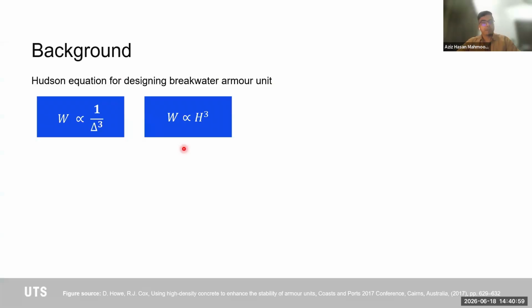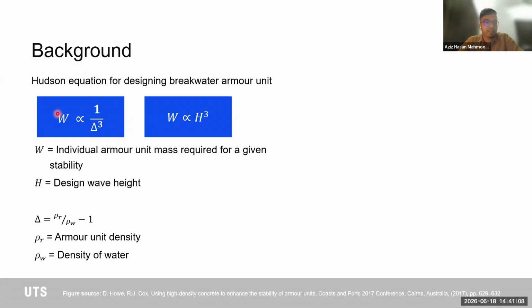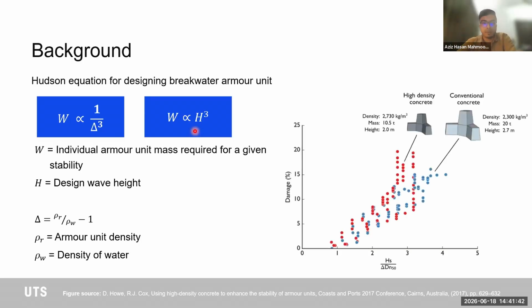So to give you a bit of background of the project, this was based on the Hudson equation, which typically correlates the individual armor unit, the armor units that we have on top of breakwater structures, which is an inverse cubic relation to the armor density, and also a cubic function of the wave height. Now, with increasing sea level rise, particularly during strong storm events, we have greater wave energy, and it does pose threats on existing breakwater infrastructures that we have along the shores.